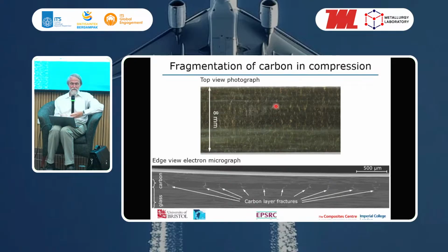Well, what you can see first of all is the top view of the specimen. We see these same sort of yellow lines that we saw in tension. So that's indicative of some local delamination around the fractures. And if you look on the edge of the specimen, then you can see there are these fractures occurring at regular spacing along the specimen, very similar to what we saw in tension.